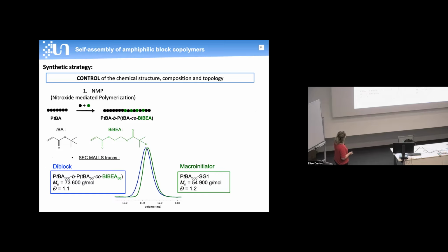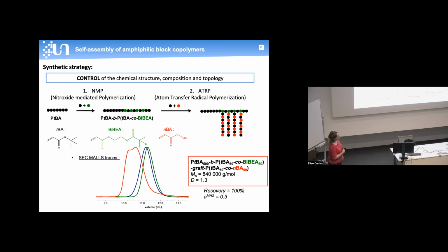So again, we made a lot of effort to synthesize the bottlebrush copolymer in a controlled manner. The first step is the synthesis by nitroxide mediated polymerization of the polymer backbone, consisting of a block of poly(tert-butyl acrylate) and a second block, which is a copolymer of tert-butyl acrylate units and bromoisobutyryl ethyl acrylate (BiBEA) units in green, which carry a bromide functionality that can be used as a macroinitiator in a third step, using atom transfer radical polymerization of n-butyl acrylate units and tert-butyl acrylate units in order to form the brush block.